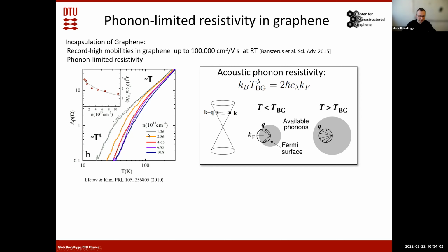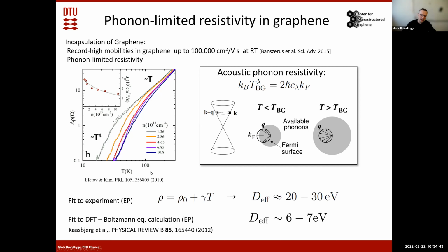So this is the resistivity for different dopings of the graphene device as a function of temperature. You see there's this interesting crossover from a linear temperature dependence to more like a T to the 4th temperature dependence. That's well understood: the crossover temperature is the Bloch-Grüneisen temperature, where the available phonon momenta start to be of the same size as the Fermi surface in graphene. But if we concentrate on this linear equipartition regime of the resistivity, then from the experiment you can fit a coefficient, which we can transform into a deformation potential. So we can estimate the deformation potential, or effective electron-phonon coupling, from the experiments.